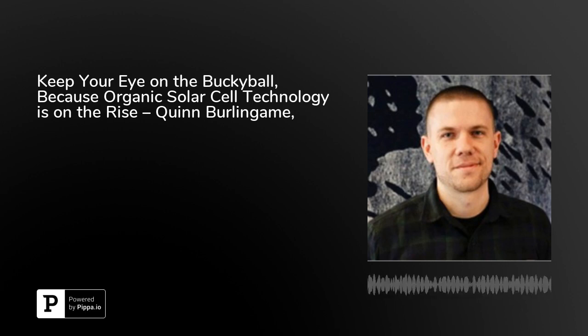How many layers can you go where there's no transmission after a while? It really depends on the material. With our basically UV absorbers, I can make it extremely thick, like a big pane of glass, before you'll really notice it. If you're looking at the peak absorption, where an organic material absorbs very strongly, you can easily absorb 99% of the light within 100 nanometers or 50 nanometers of the material. So they interact really strongly with light, which is why they're such great optical materials.